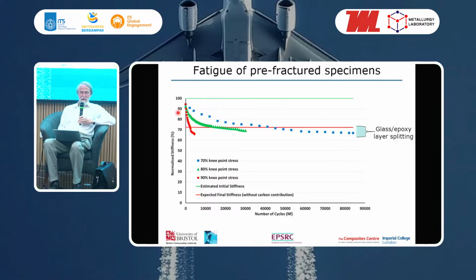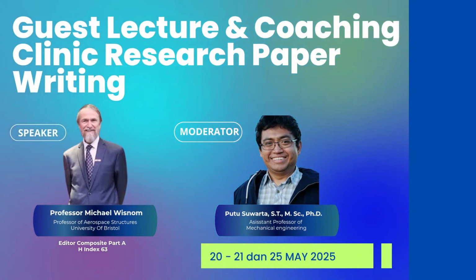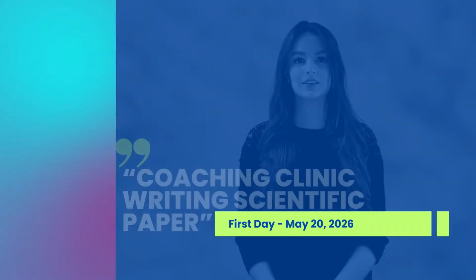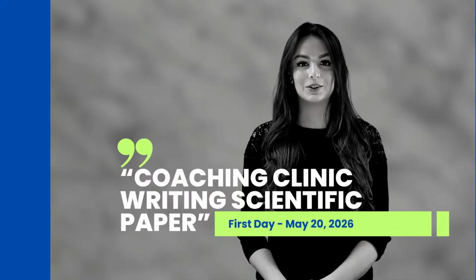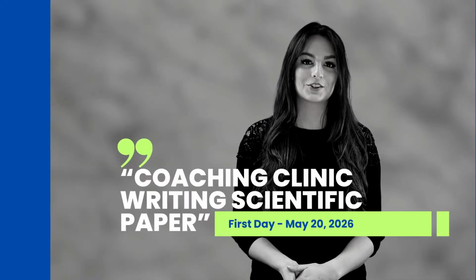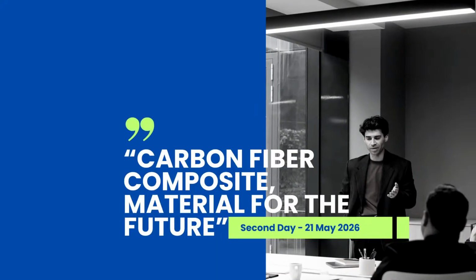So the 4-point bending results here show that at 0.5% strain, which is the failure strain of those M55 fibers in compression, at 0.5% strain, we see a change in slope. So that's what's happening.